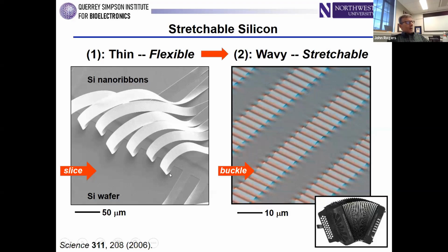The other thing about making a material thin is it means that you can minimize the bending-induced strains associated with bending to a given radius of curvature. So it not only reduces the flexural rigidity, but it increases the bendability before the onset of a fracture, which will occur at about a 1% tensile strain in silicon. So that becomes kind of interesting. And then you can think about these ribbons and membranes as building block materials you can mount onto a flexible or a stretchable substrate, to produce a system that has mechanics that begin to get closer to those associated with biological tissues.